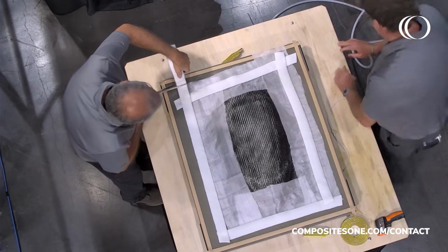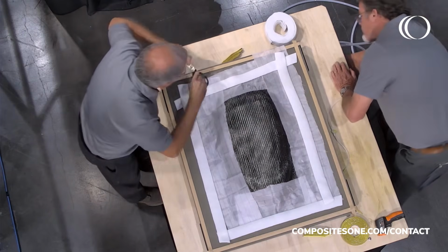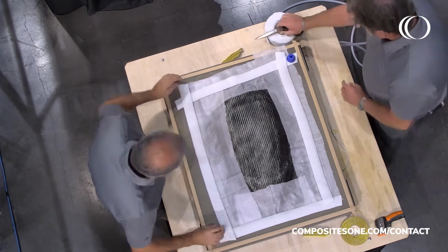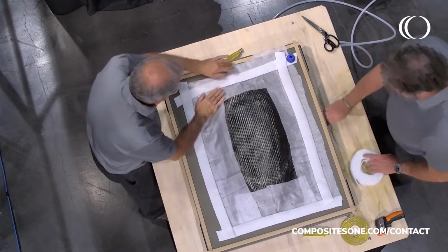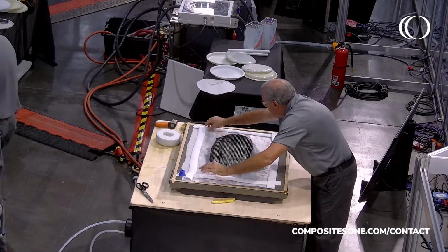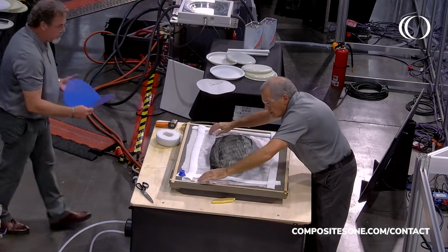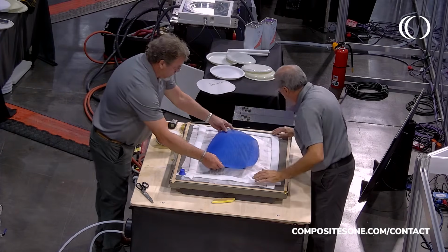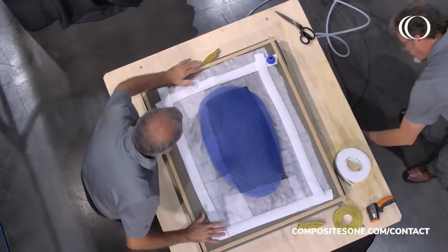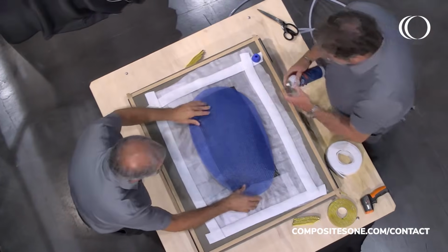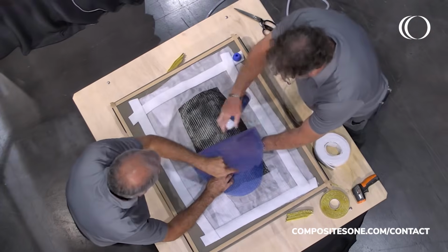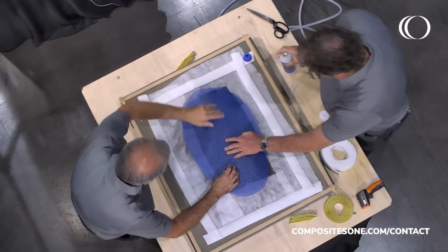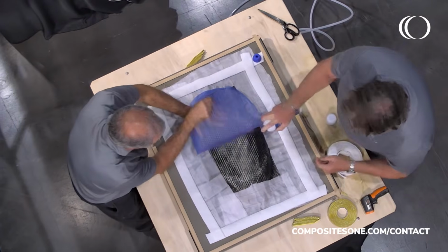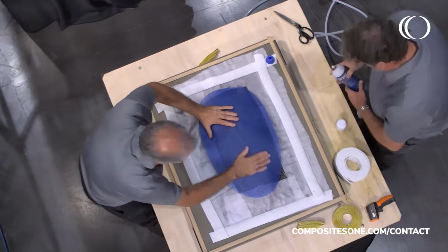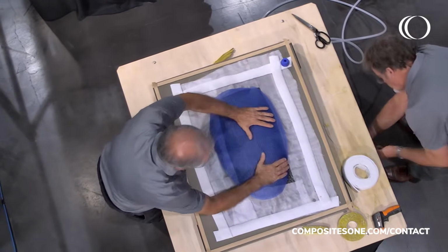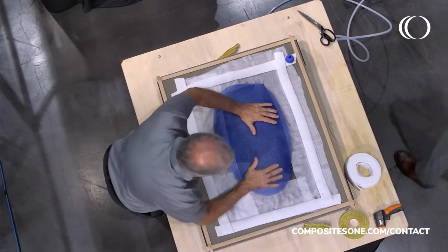And with this tool, once we get through that design phase, we design the circuitry, we design the sandwich plate, and then we take into account the fasteners and the sealing surfaces as well. We seal the tool, and we anodize the tool as well for surface finish. Our focus at Origen is to get surface finishes out of the machine as good as possible to reduce any handwork that's associated with mold surfacing. So one of our specialties is getting extremely good Class A surface finishes out of the machine. With this tool, again, we love the footprint, the scalability, and also the ability to cool.